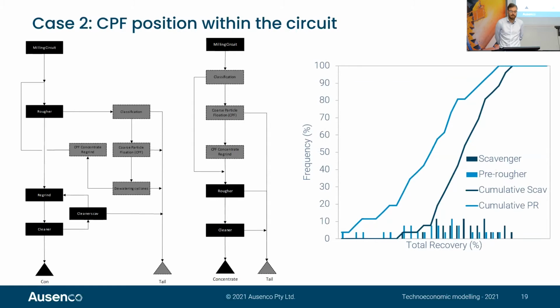In the second case study, we looked at where coarse particle flotation would be best positioned within the circuit. Now, the circuit on the left there has coarse particle flotation in a scavenger duty, so following the rougher, same as what was considered at Cadia. But there's a lot of people wanting to put the coarse particle flotation in a pre-roughing duty in front of the rougher, and there's expected benefits from that. However, when we've pulled this into the technoeconomic model and looked at the impact of densities around the circuit and what needs to be done around the water balance and a number of other key considerations, actually putting the coarse particle flotation in a scavenger duty has improved benefits.